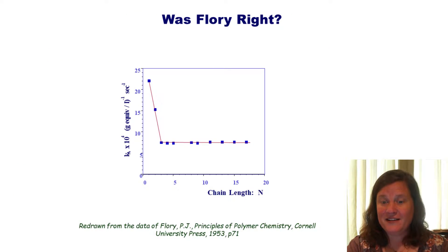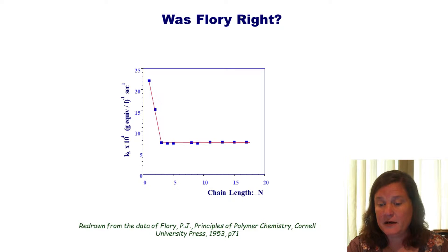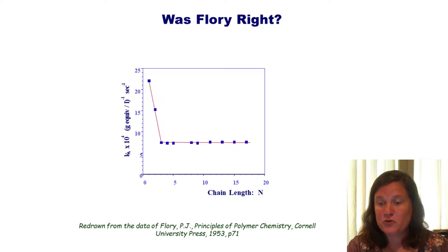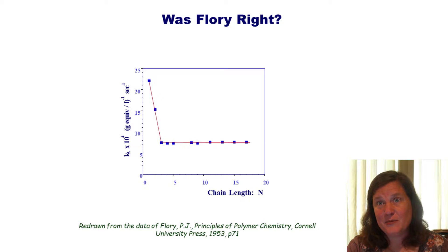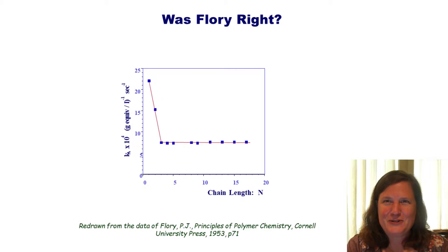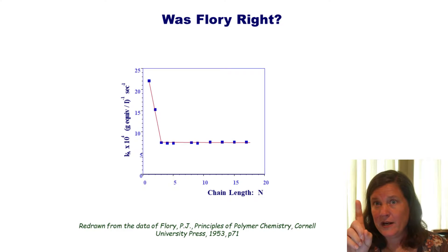Let's look at this plot — is Flory right? This is real data from the 1950s that Flory published, and it's quite amazing how little variation there is from trimers on. The rate constant of an esterification just doesn't change once you get past monomers and dimers. So reactivity is independent of chain length, except for monomers and dimers. That's a really good assumption, and it's important because now we need one rate law as opposed to a rate law for every length of chain.